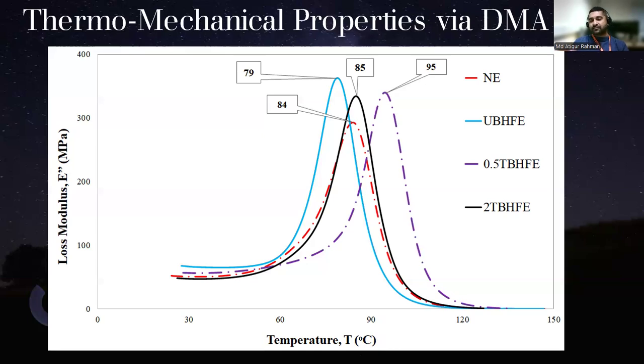We pick the glass transition value at the peak of the loss modulus rather than the damping factor, because after the loss modulus peak the material becomes a little bit more flexible. So the loss modulus peak is the conventional peak we should take if we want to suggest the material for primary structural uses, I should mention. However, if we see the untreated fiber, which is colored blue, the Tg value dropped to 79 degrees centigrade. So the thermomechanical properties deteriorated.